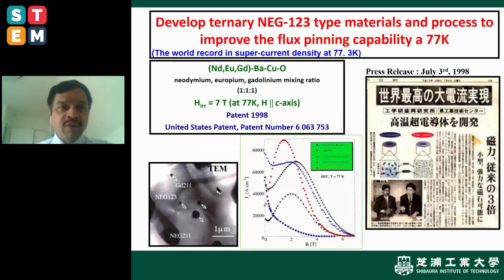Everybody is working on this with different materials, and I concentrated on improving the performance. Everybody says single grain materials like yttrium, neodymium, samarium, but after a certain field you can see that for YBCO the JC almost all goes down, while in the case of NdBCO there is a little bit of improvement at 2 Tesla.